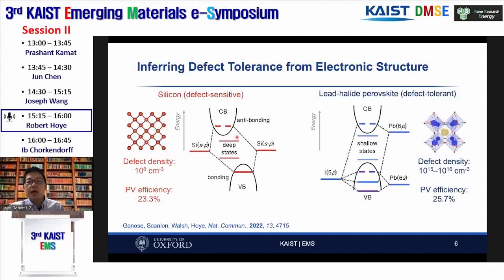So one of the reasons why this comes about is through a property called defect tolerance. And what you see on this slide is an electronic structure model to explain how defect tolerance may come about. So if we look at silicon, we have this covalent structure, and the sp3 hybrid orbitals from the silicon atoms hybridize in turn to form these bonding and antibonding states across the band gap. As a first pass approximation, if you were to introduce a point defect such as a silicon vacancy, your dangling bonds will interfere to create defect states, and those defect states will approximately form close to where your original atomic orbitals were. In this case, these original orbitals are in the middle of the band gap, so you would tend to form deep trap states. And these deep traps are very harmful to the performance, causing high rates of non-radiative recombination.